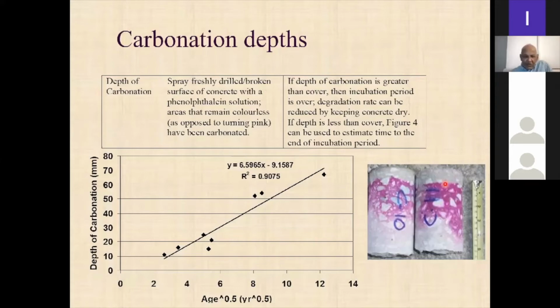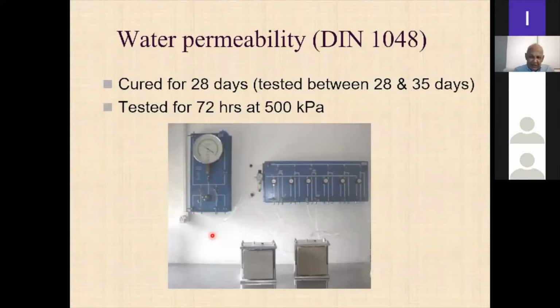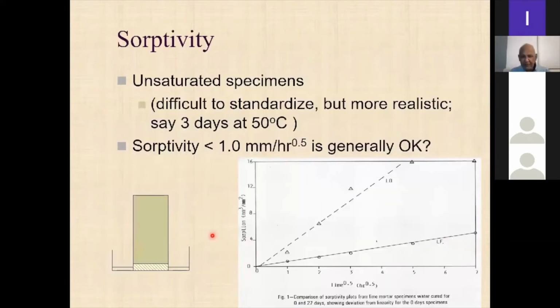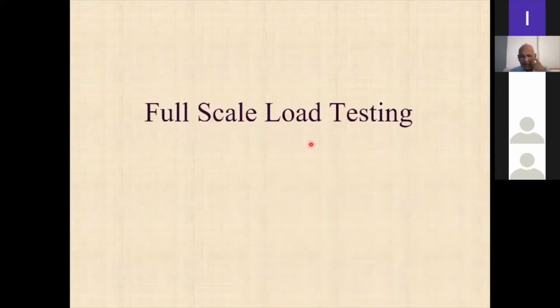Right. So these are based on some sort of results that we have taken over the years. Okay. So we can do this water permeability test. That is not so much an in situ test, but that is more to approve the concrete before it is used. Right. So these are some results. Sorptivity we can do on the core itself. But there isn't very much guidance on which sorptivity values are acceptable. Maybe there is more recent literature on this, but typically these are the values that we used to use earlier, right? I will not go into details of that.